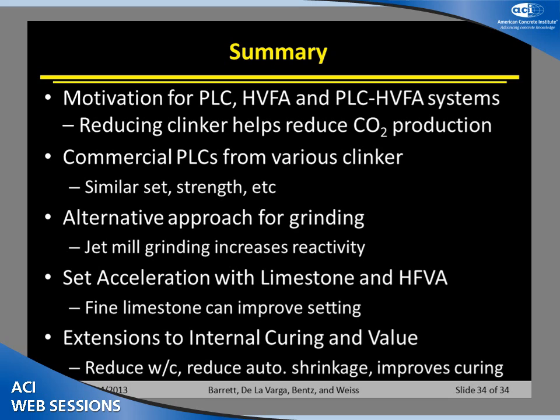How can we grind nano limestone? The nano limestones aren't being ground. What I was mentioning with the jet mill grinding is we're looking at more conventional limestones, fly ashes, and cements. With jet milling technology, you really don't grind things smaller than 1 to 2 microns. You can't grind materials finer than that. The nano limestone is a precipitated one that comes out of Canada, and Taisato would be much better to answer those questions than I would, and I'd be happy to give you his email.